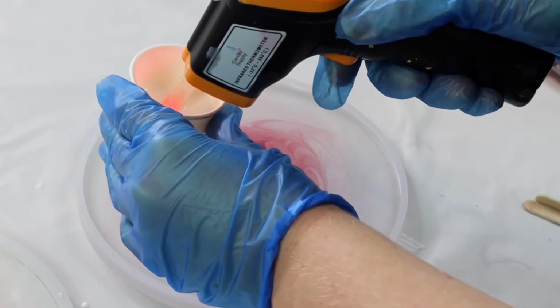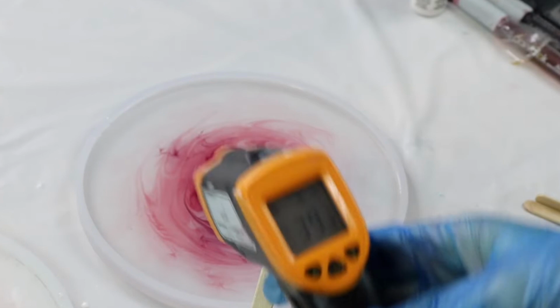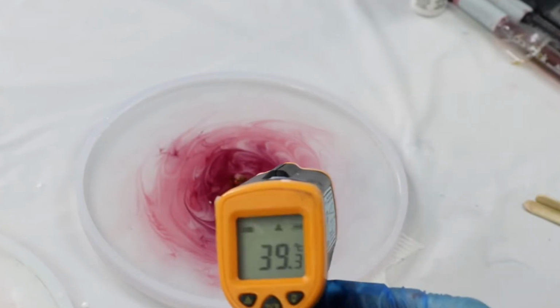Now, whenever I do create a 3D bloom effect, I try not to go by timing but by temperature, because as we've talked about previously, as the resin does start to set, it will get a bit warmer, and so the temperature is going to go up, and that is an indicator to me about when I can then add my petals in on top of my clear resin to create that bloom effect.